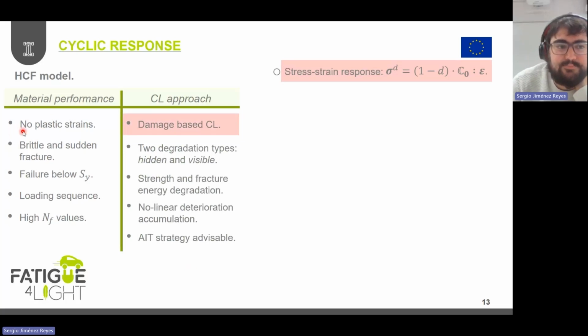So in order to achieve no plastic strain accumulation identified in this high cycle fatigue process, what we need to work with is a damage-based description for this high cycle fatigue constitutive law, which is the alternative to the plasticity constitutive model, right? As we've seen previously. This results in characterizing the stress in our high cycle fatigue model in this way, which is the same one that I presented previously for the isotropic damage case.